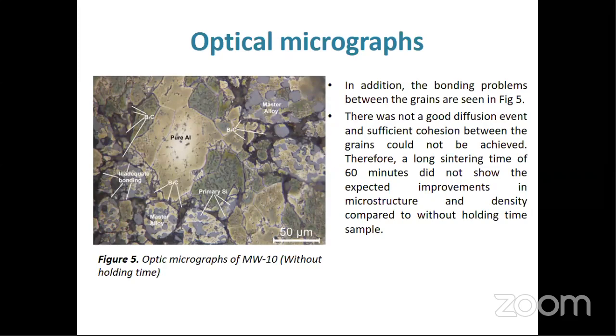In addition, the bonding problems between the grains are seen in figure 5. There wasn't a good diffusion event and sufficient cohesion between the grains couldn't be achieved. Therefore, a long sintering time of 60 minutes didn't show the expected improvements in microstructure and density compared to the without holding sample.